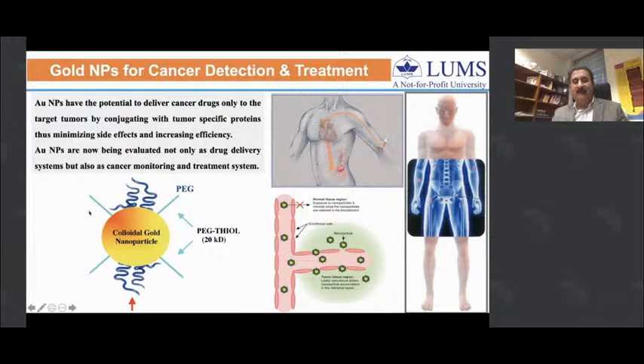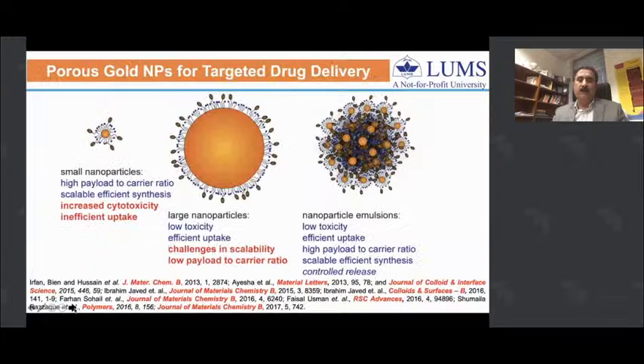More recently, there has been a lot of work on the size effect of these nanomaterials, and it has been found that particles which are between 50 to 100 nanometers are really useful for these type of applications. But if you use 50 to 100 nanometer particles, they have smaller surface area compared to a collection or assembly of these nanoparticles of the same size.